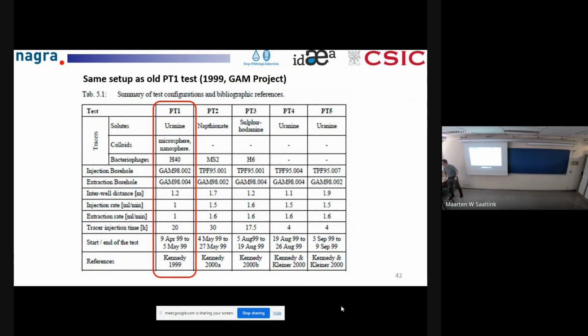Right. In this same dipole between these two boreholes, there was another experiment in 1999. So we're using basically the same setup. This PT1 test used uranine and other tracers. So you have active injection and active extraction at 1 milliliter per minute. Injection of a pulse of the tracer was done during 20 hours. And then after that, you inject water, but without the tracer. So you measure the breakthrough.